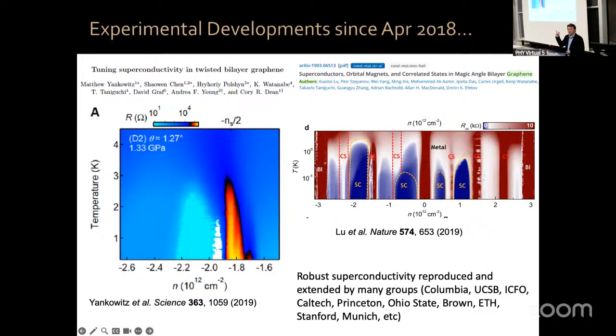Because you get closer to that flat band condition at a larger angle, together with collaborators from Harvard, we predicted theoretically what the magic angle condition would be as a function of pressure. So they knew exactly which pressure to dial in to get the flat band condition. When they measured the devices at that high pressure, 1.33 gigapascals in this case, they were able to measure correlated insulators and superconductivity. This was a very nice demonstration that it's the flat band condition which enables you to measure this strongly correlated physics.